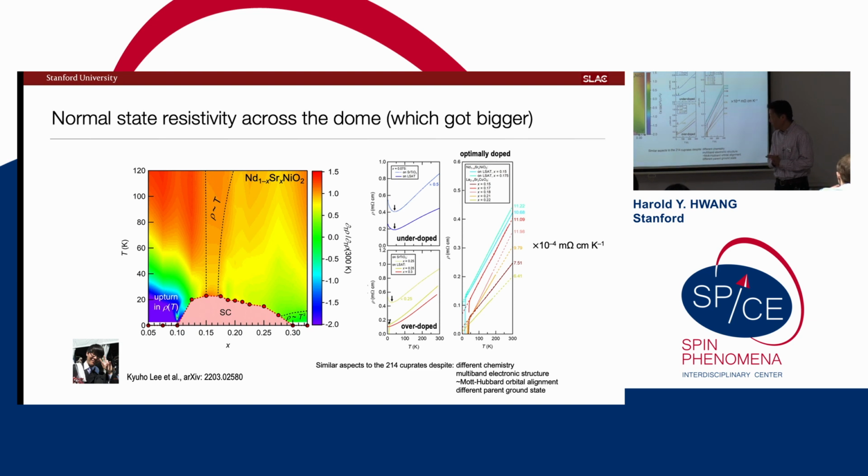My maybe slightly uninformed opinion is to be biased against that in the following sense. We've done even very high field experiments, and this doesn't really move around even with aggressive magnetic fields. I would have expected these Kondo singlet type of ideas to be responsive to that. And if one goes back and tries to think about real numbers for Kondo scattering and their density, at least for me, that scenario is not very tight. But I should say, there are strong opinions on the other side of that coin right now.